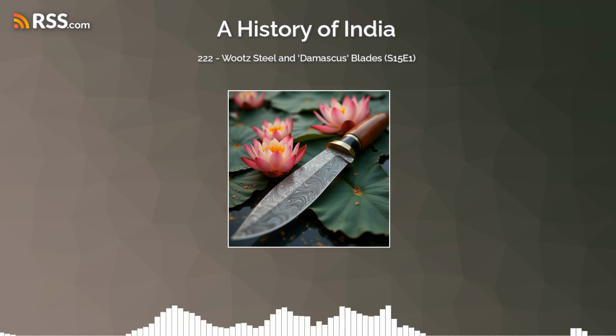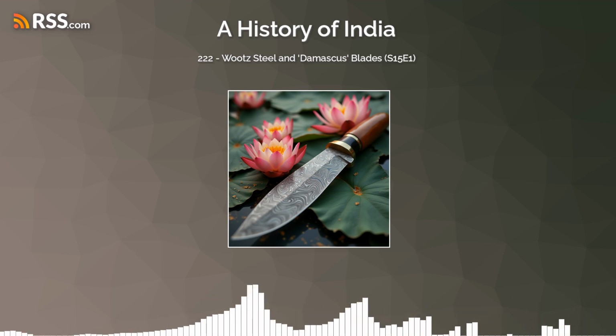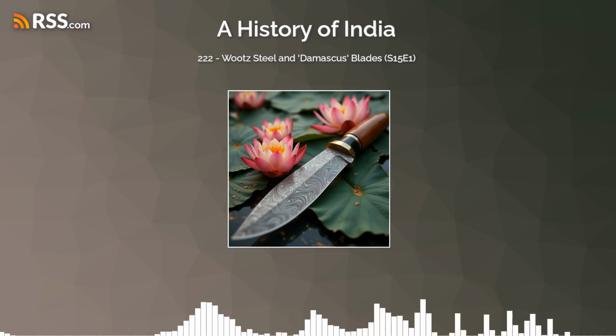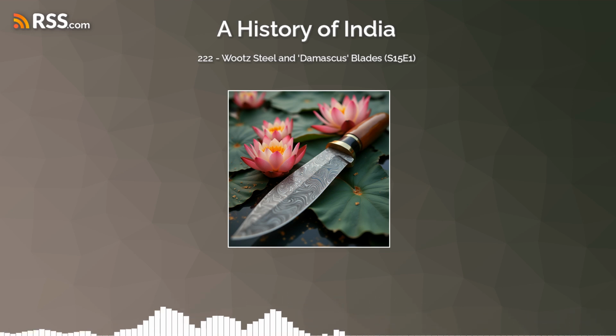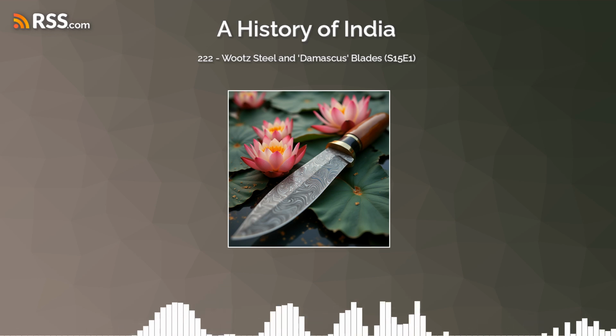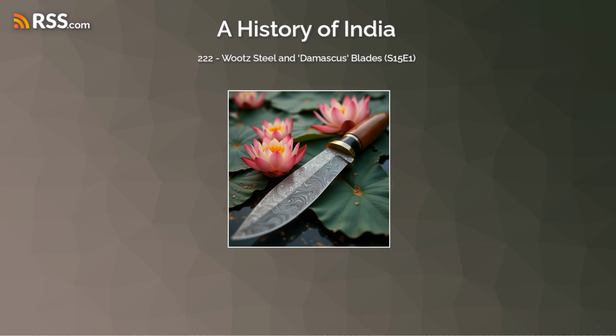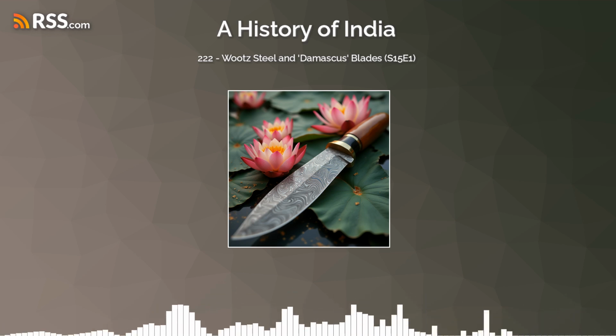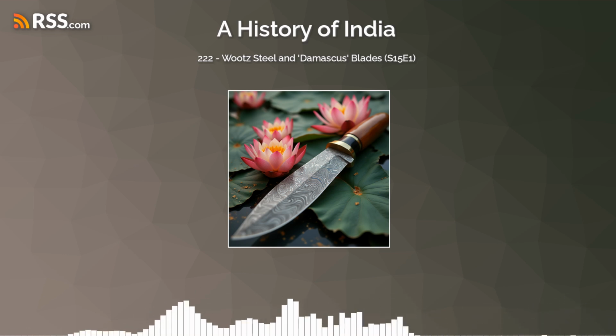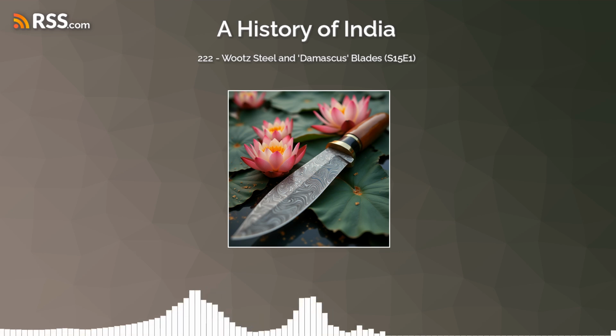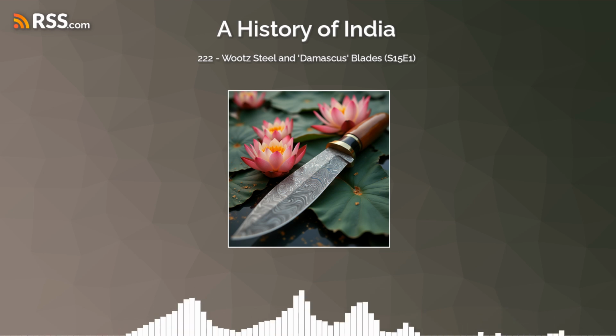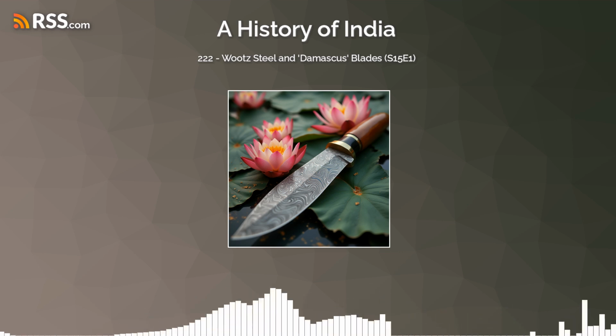Some even theorize it acts like a tiny photonic crystal, which is fascinating. The visible pattern we see on a finished blade comes from macroscopic sheets or bands made up of these microscopic carbides, the cementite, distributed within a matrix. That matrix might be tempered martensite or pearlite in the higher carbon Wootz, or ferrite and pearlite in slightly lower carbon versions. The exact structure depended on the initial ingot chemistry and, crucially, how it was cooled in the crucible and then heat-treated during forging.